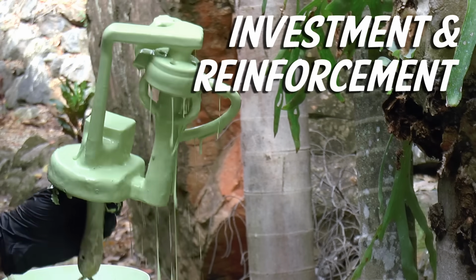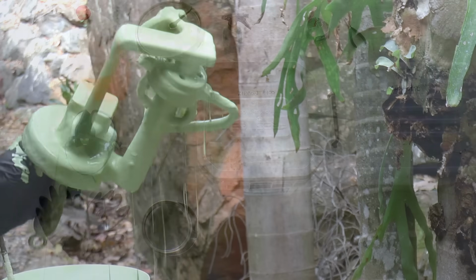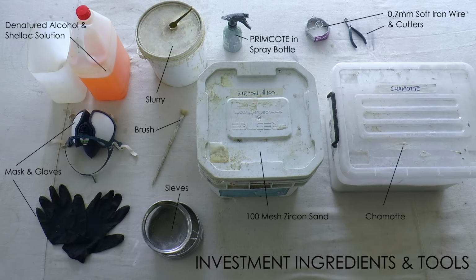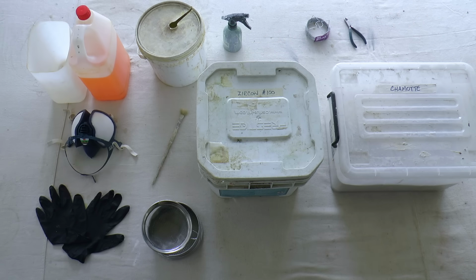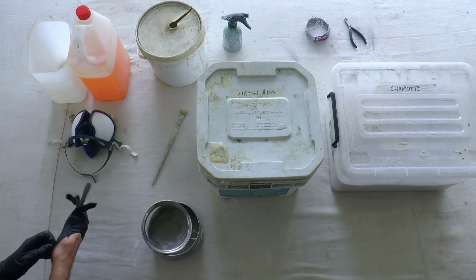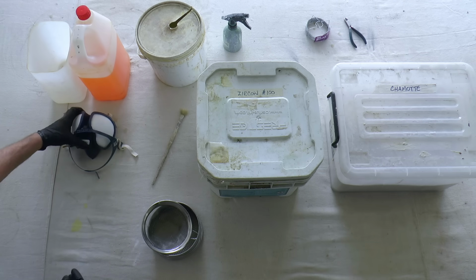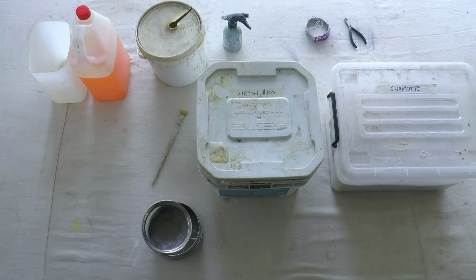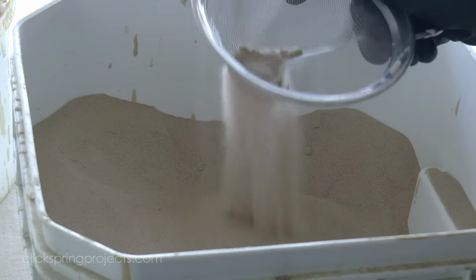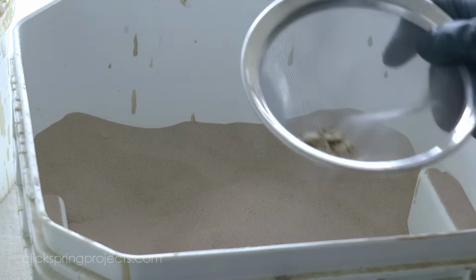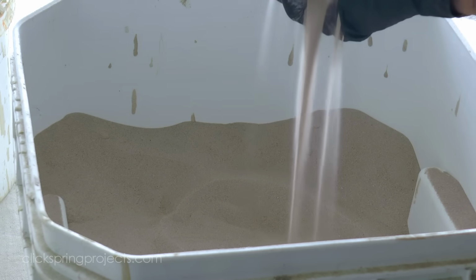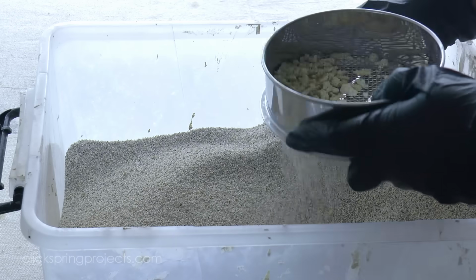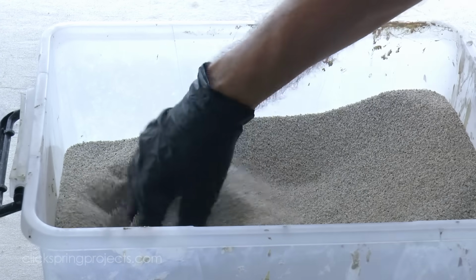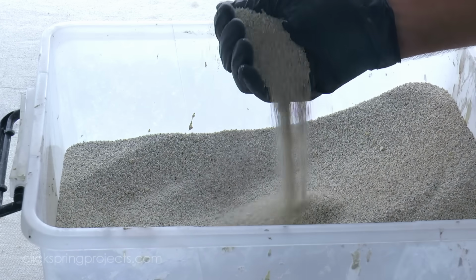Okay, so once the slurry is applied to the pattern, it's usually augmented with various refractory sands to create a solid layer of ceramic. There are several choices of sand available, and 2 commonly used are zircon sand in a fine mesh and a coarser refractory material known as chamotte. Zircon is a hard mineral sand with a natural heat resistance, which makes it perfect for the first metal-facing layers. Depending on the pattern, I generally use zircon sand for up to 5 of the initial layers. Chamotte is a fairly light, coarse material, suitable for the remaining layers.